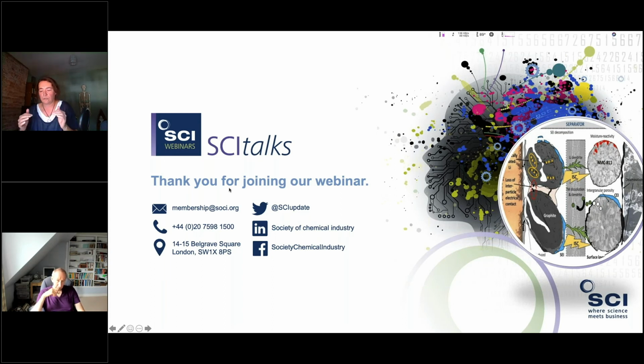And as well as the physical engineering of surfaces, there are more in situ approaches such as additives to electrolytes that can control morphology to create more uniform plating rather than high aspect ratio dendrite growth. A lot of areas in that domain are making leaps and bounds. To mention companies, Oxis Energy, who've been developing lithium sulfur batteries, have done very good work on passivating the surface of the lithium anode to try and better regulate that detrimental growth of lithium. So there's a lot of effort and enough lithium in the world to hopefully succeed at that.